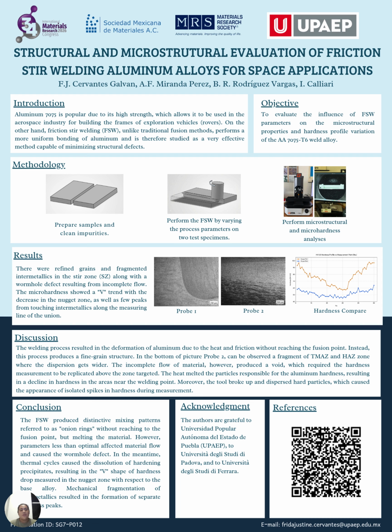The methodology used was first to prepare samples and clean impurities. Then we perform the friction stir welding by varying the process parameters onto test specimens, and perform the microstructural and microhardness analysis.